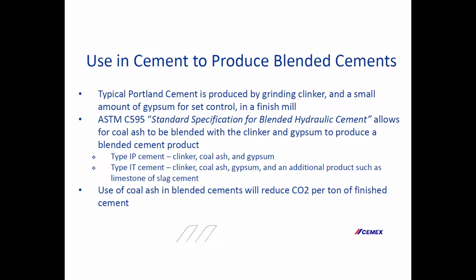So that's clinker, the coal ash, and the gypsum. There's also a Type IT product, which is a ternary or 3-product type of cement, which might have clinker, coal ash, gypsum, and additional products such as limestone or slag. And so these blended products are becoming more and more important for the cement industry because it helps lower our CO2, which is very important. There's a lot of pressure on the cement industry to do so, and we're working very hard in these blended products to help do that and to lower our CO2.